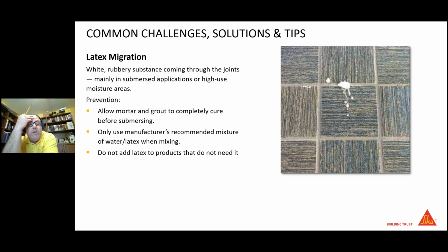So allow mortar and grout to completely cure before submersing. That's a big one. When you're doing pool applications, fountain applications, where there's tile or a waterfall type of installation from, let's say, a sauna going down into a pool, they'll install the tile, they want to put the water on it and have that water running through it. What's going to happen is it's not curing out properly. That water is going to get behind it and come out and start pushing the latex that's in the installation out to the surface, causing this unsightly rubbery white stuff. So we need to make sure, again, whatever's on top of it, our mortars, our grouts are completely cured. In most cases, that's 28 days prior to submersion.